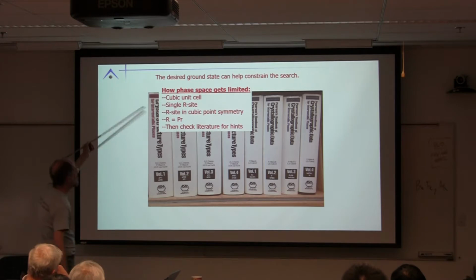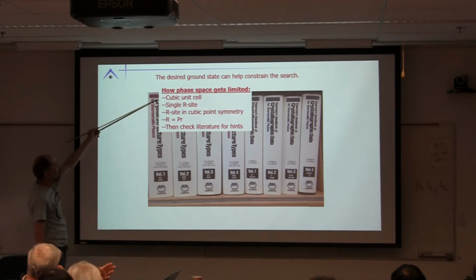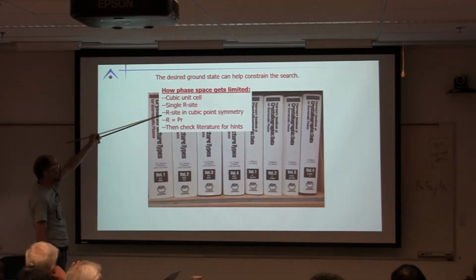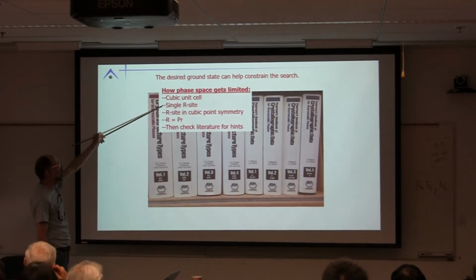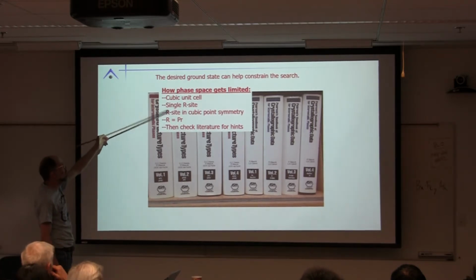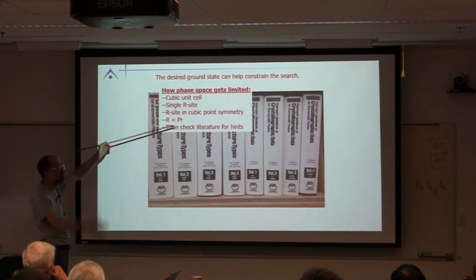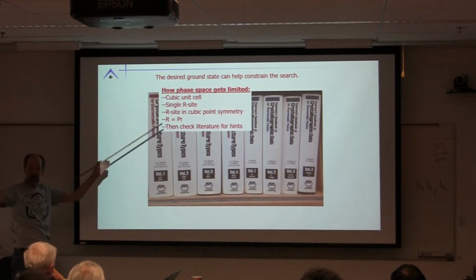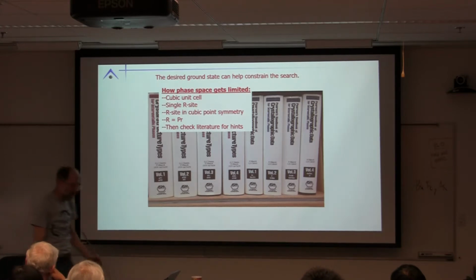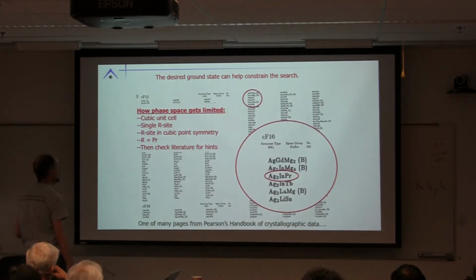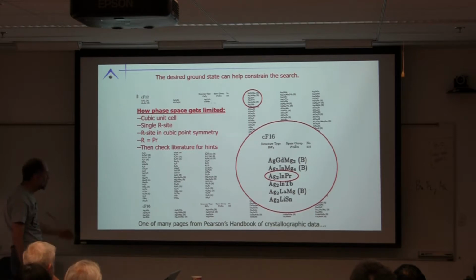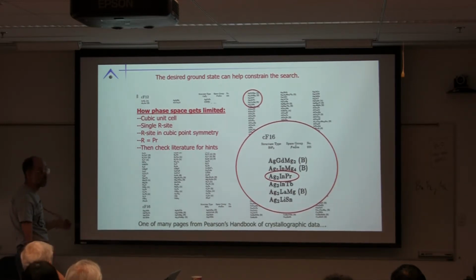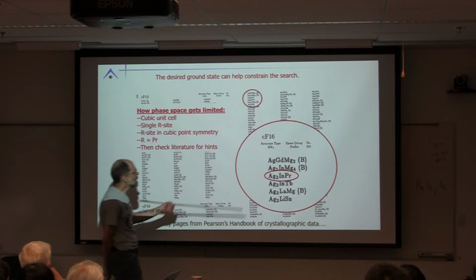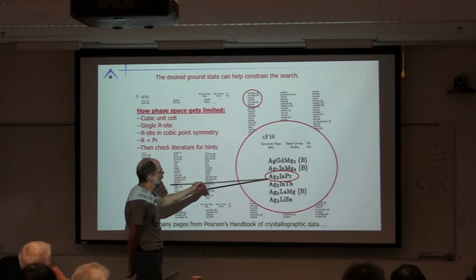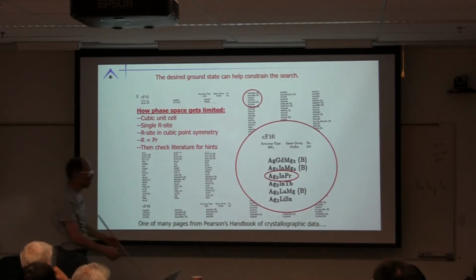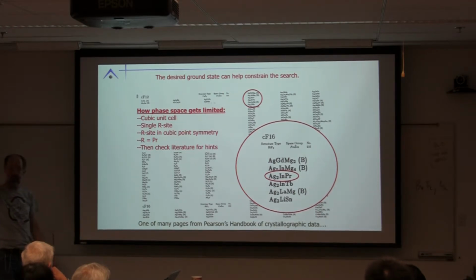So, how do we use these? Well, we want a cubic unit cell because we want a cubic point symmetry for a single rare earth site. So, cubic unit cell, single rare earth site, rare earth in cubic point symmetry, rare earth equal praseodymium. This is a cascade that starts narrowing what you look at. If we look at Pearson's, here's one of the many pages out of Pearson's. Here's CF16, otherwise known as Heusler. And if we look at it, underneath all of this you have silver 2 indium praseodymium. Cubic point symmetry, praseodymium.